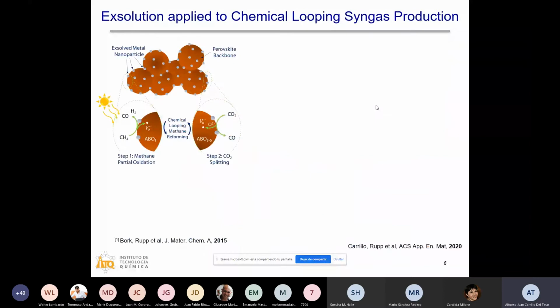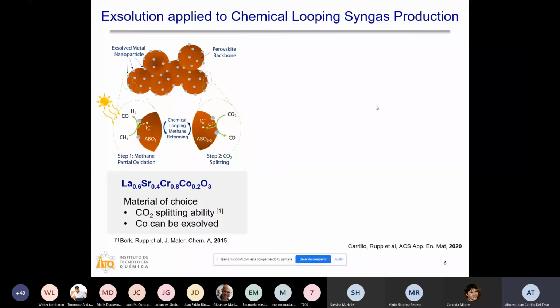So this is our schematic of what we are studying here. We will use the solar energy to drive the methane partial oxidation. We put our metallic nanoparticles to improve the kinetics and the catalysis of this process. And in the second step, we will inject CO2. It will reoxidize the reduced material, and we will produce carbon monoxide. And this is work that I started at MIT with Professor Rupp. And we started with this material because previous work by my good friend Alexander Bork showed that this material can actually split CO2.